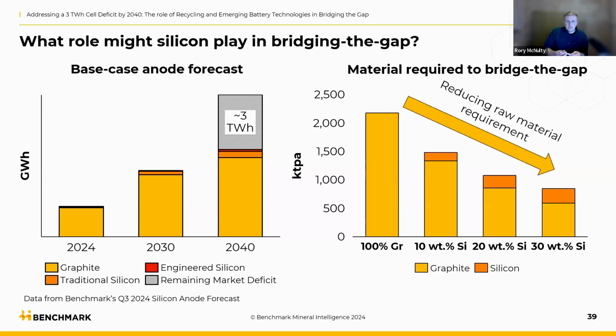If we look at some relatively ambitious scenarios for silicon adoption, we can see that raw material requirement in tons to bridge that gap can reduce quite significantly. So with just 30 weight% silicon, we can reduce that by more than half. Now, really the key point to make here is that today we're seeing relatively low weight percentages of silicon materials. That 30 weight% scenario will require a huge amount of technical progress, a huge amount of commercial adoption, and widespread silicon adoption across the globe.